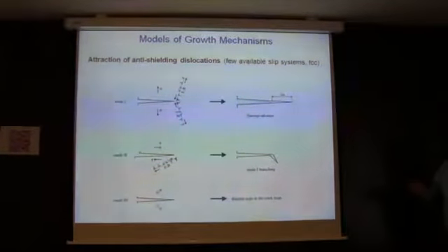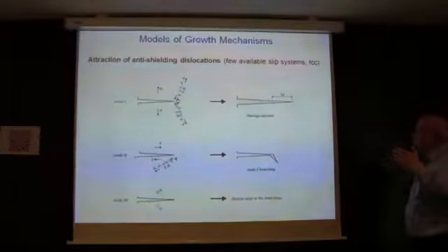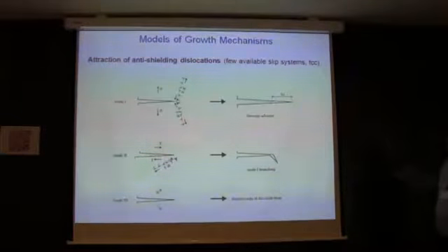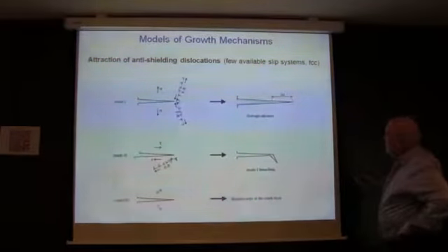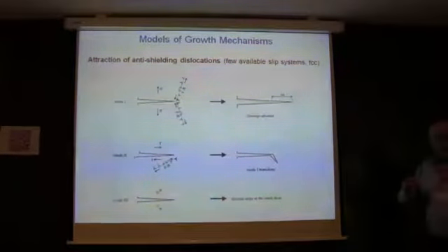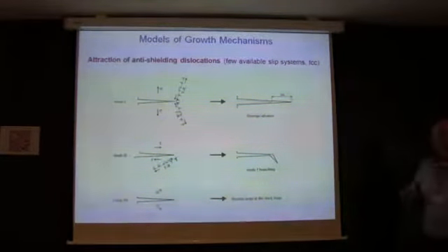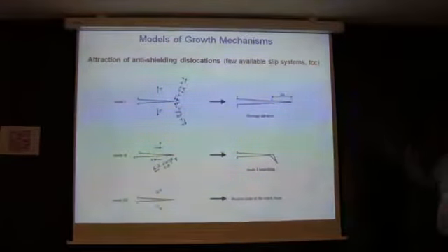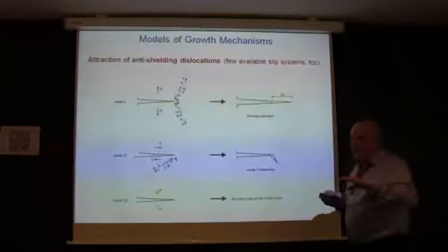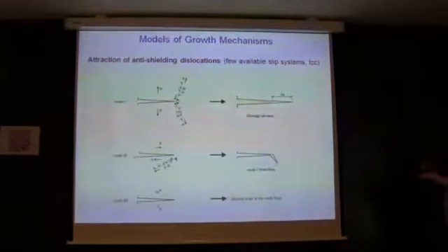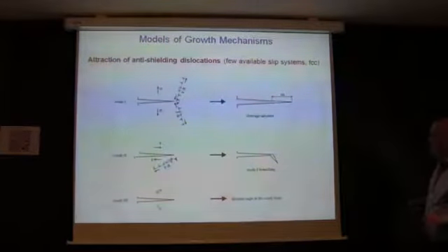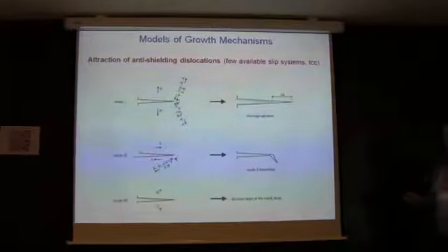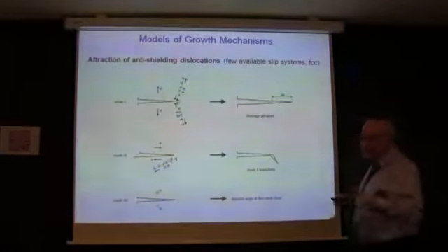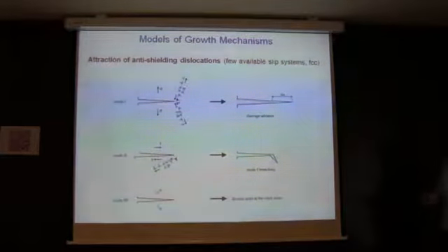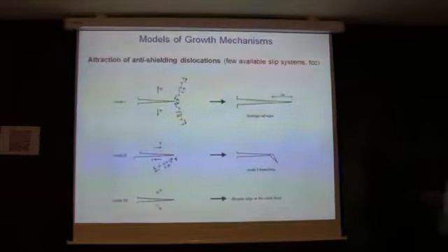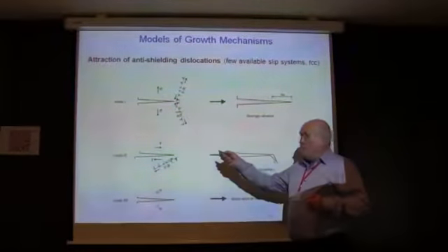Anyway, so this was the emission model, or we also say the deformation model. But there is another model that works if you do not have too many available slip systems around the plane of maximum shear. And this is FCC systems. The available slip systems are at 90 degrees, so that's too much. And so Needleman and others proposed a model which is based on anti-shielding dislocations, it means absorption of anti-shielding dislocations. They actually proposed it for mode 1.